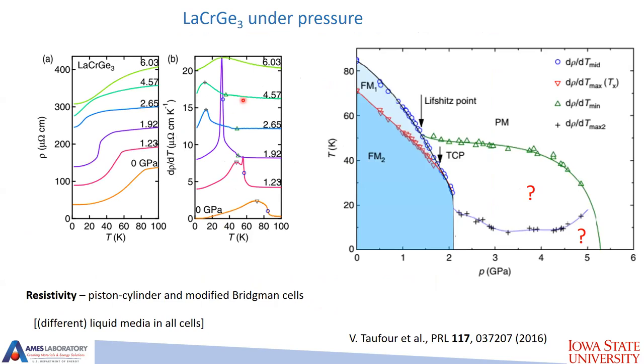So what we did first, we looked at the transport, at resistance at different pressures, using two pressure cells, piston cylinder and modified Bridgman, with liquid media in both cells, liquid media, of course, at room temperature. So you can follow these transitions. It's better done in derivatives. And you can basically get your phase diagram.